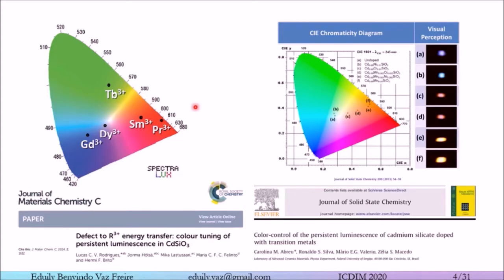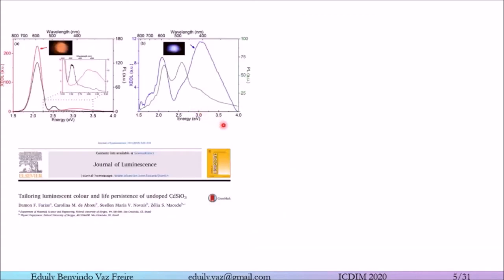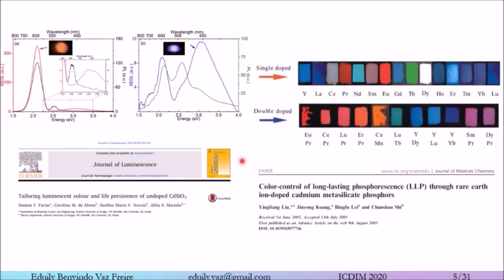Okay, and now another important fact to be said is that even in pure materials, without any doping, it has long-lasting intrinsic luminescence in two regions of the visible spectrum. In the first region, we have a luminescence in red, and in the second region, in blue, as demonstrated by Freire.